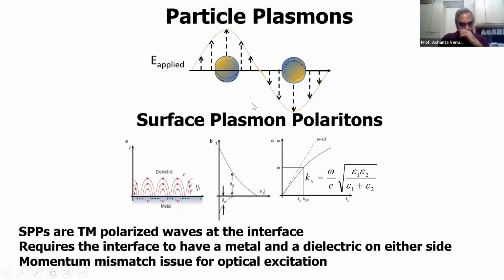Right? So similarly, if you have a metal and a dielectric planar interface, you deposit metal on top of a dielectric or dielectric on top of metal, you have free electrons at the surface, and under certain conditions, you can excite a charge density wave. That is, you have a large number of electrons, so large minus signs at one position, and a smaller number of electrons at another place. Right? So you can have this charge density wave propagating along this interface.